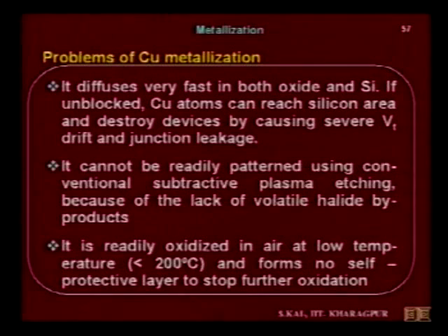The third problem is it is readily oxidized in air at low temperature. Even below 200 degrees centigrade, it readily oxidizes and forms no self-protecting layer to stop further oxidation. So these are the key problems in copper metallization. It is readily oxidized in the presence of air at low temperature, even less than 200 degrees centigrade. That is a major problem.